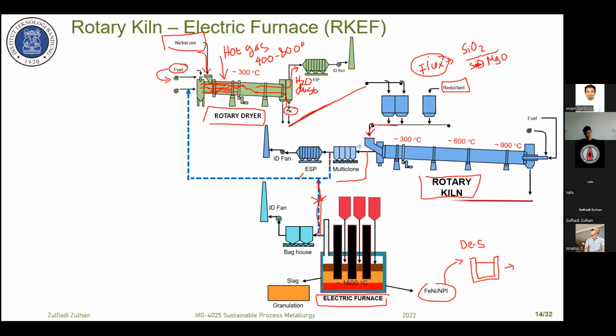Flux is added. It could be dolomite or limestone to adjust. Also, in some cases, if you do not have any copper cooling in the furnace, in order to increase the lifetime of the refractory material, we also add flux like limestone. In that case, we can increase the lifetime of the refractory to roughly 5 to 6 years.